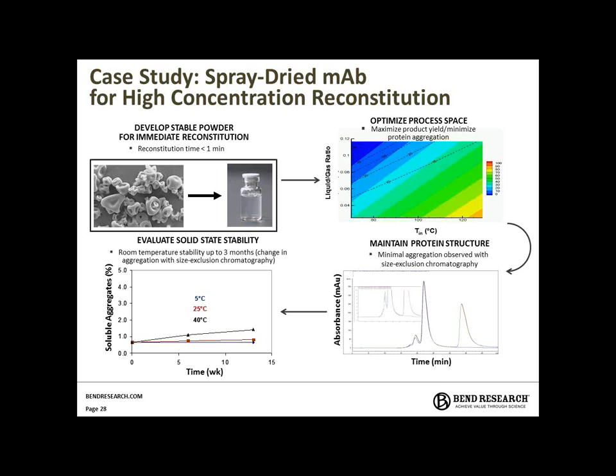We needed to optimize the process space using SEC, and as Devin mentioned previously, using the operating space guidelines, we developed a spray dry area that maintained the quality of the powders, looking at T in and T out. We also used SEC to look at the quality of the API, or in this case the mAb, coming out of the formulation after resuspension. The team also performed a 3-month stability study at 5 degrees Celsius, 25 and 40, and saw that we did see some aggregation form over time, but mostly we were able to mitigate the aggregation and produce a high-quality powder using a rational spray-dry process and formulation.